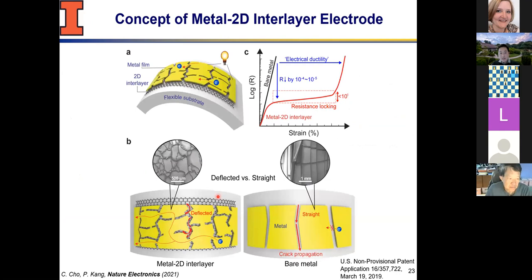What we actually saw, and I should really say this is by accident, for the most part, was that we were simply interested in comparing the fracture behavior of metal on flexible substrate, but we were also interested in having another 2D material, in this case graphene, underneath it. And the hope, or thought, was that graphene is also conducting, so maybe this will help us achieve higher electrical failure strain. So that was just a thought. And it turns out it kind of delivered that, but the mechanism of doing that was very different from what we expected. So that's what I mean by unexpected.